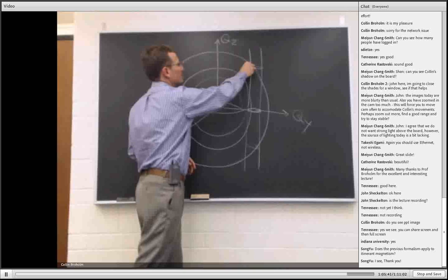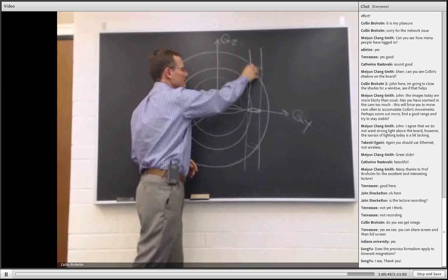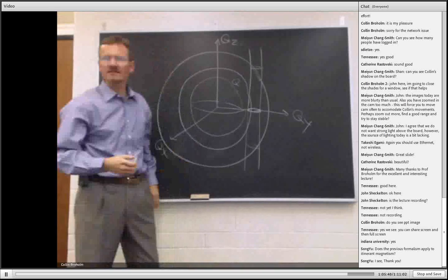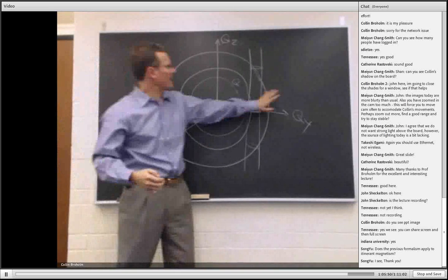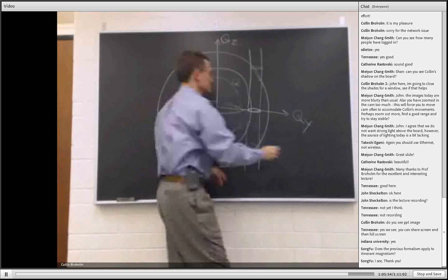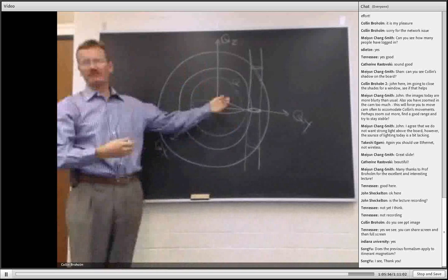And in fact, I'll keep having this rod cut through my Ewald sphere, even as I go to larger and larger momentum transfer. It's not until I meet the next tube, which might lie out at some greater momentum transfer, that I might see a sharp feature in the pattern again.